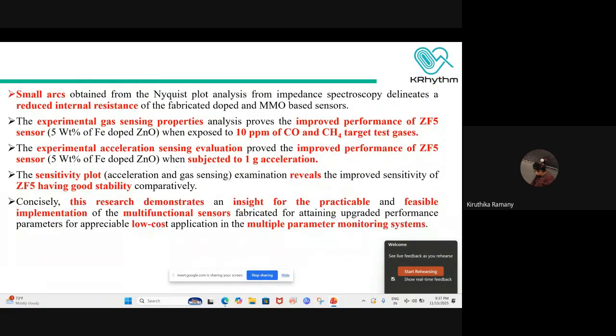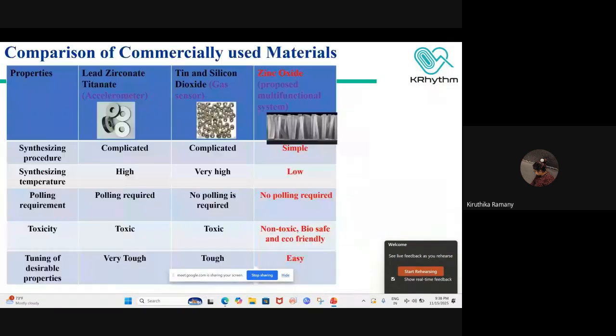We found that the experimental gas sensing properties proved improved performance of the ZF5 sensor when exposed to 10 ppm of CO and CH4 target test gases. Similarly, ZF5 had better acceleration sensing properties, and we went for the stability analysis also. We repeated the experiment every 15 days to find its stability and reproducibility, and we found that it had very good stable and reproducible results.